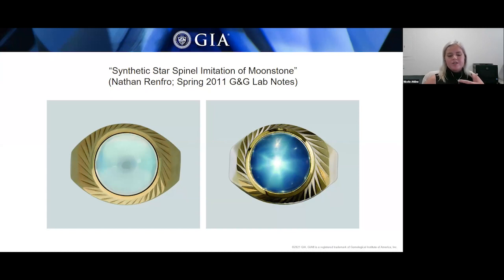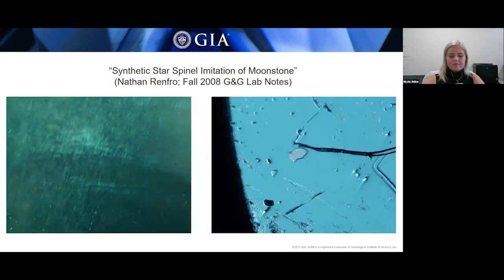Standard gemological testing revealed the stone to be actually a laboratory-grown spinel. It had a spot RI of 1.72, and it did have strong green fluorescence under shortwave UV light. Internally, the stone had a dense network of dislocation stringers that were oriented crystallographically throughout the stone, and it's the presumed source of the asterism. You can see that in the photomicrograph on the left.